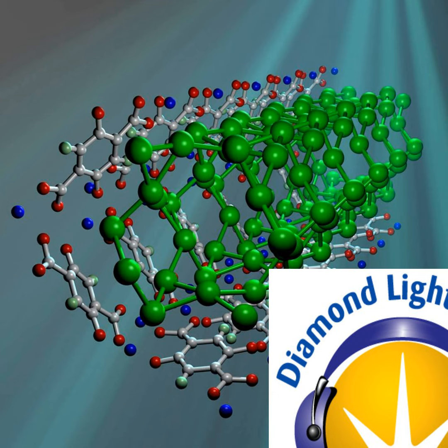And so what did they actually find by looking into this? Well, the team found that the observable changes to the coloration of the bone are not just the result of a toughening mechanism. They also indicate deeper damage below the surface in small bones. The team also showed that whitening can be used to track this damage, and so it can provide a useful tool to measure bone toughness. So we now have a new method of measuring the quality of small bone samples, and that's something that's really important to biomedical research into the effects and treatment of disease. And theoretically, this methodology could be used to measure the quality of other similar materials. As such, the findings could have important industrial applications.